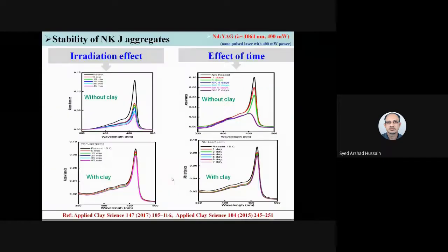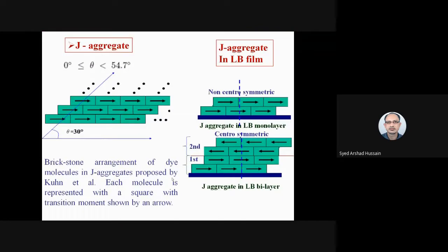For second harmonic generation, SHG, the material should be non-centrosymmetric in nature. If there is symmetry, then there is no second harmonic generation. In the LB technique, we can organize material in a suitable way so that even if there is symmetry in the molecule, the whole structure as a whole is non-centrosymmetric.